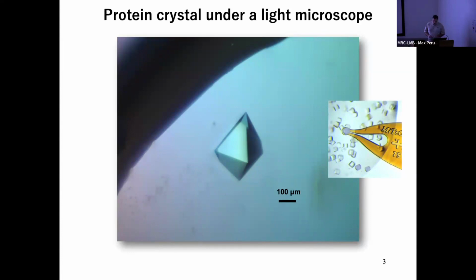Macroscopic protein crystals are assessed under a light microscope. Single 3D crystals with sharp edges and symmetry, like the one shown here, are fished out with microloops for X-ray diffraction tests. The integrated diffraction spot's intensity is directly proportional to the volume of crystal illuminated, and hence crystals must have dimensions of at least 20 to 30 micrometer, even larger when testing them with our in-house X-ray diffractometer.